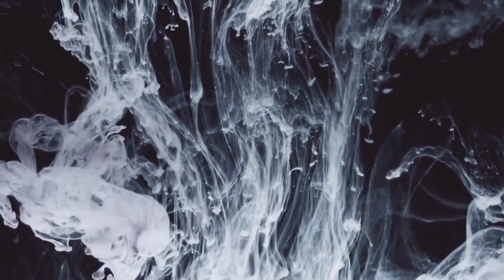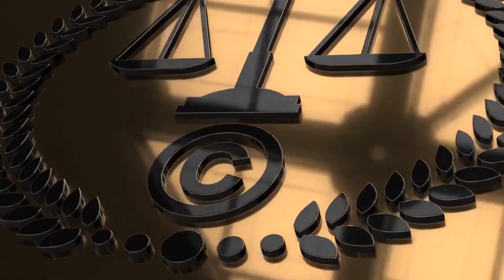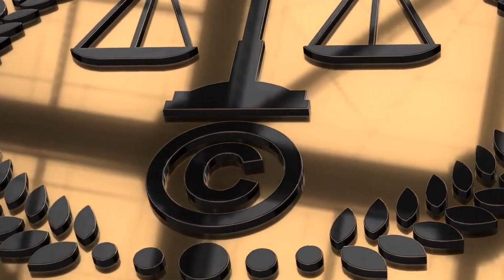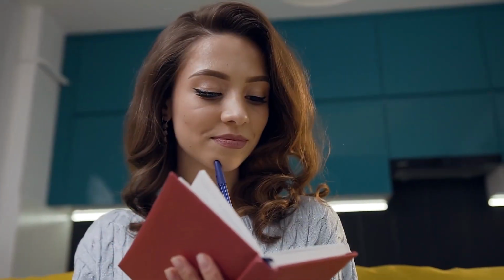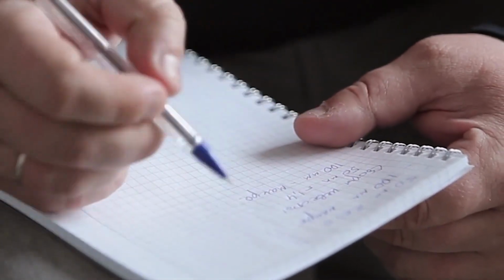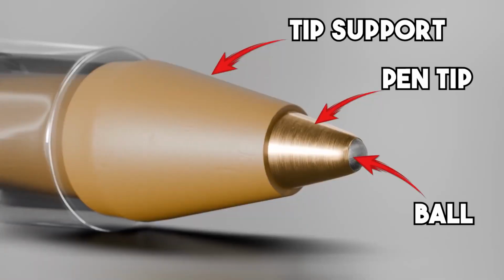Without this follower, air would enter the rear of the tube as ink is consumed, creating a partial vacuum that reduces flow rate by up to 60% in the final third of the pen's life. The entire filling and sealing operation must be completed within 4 hours of ink mixing.